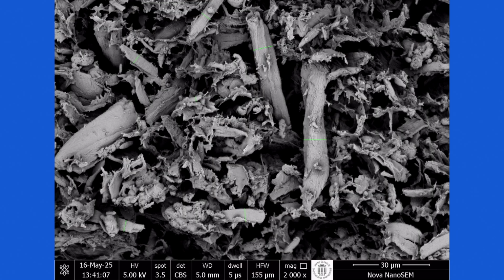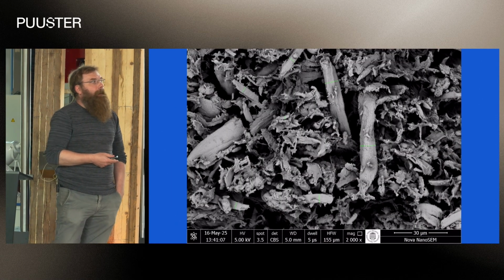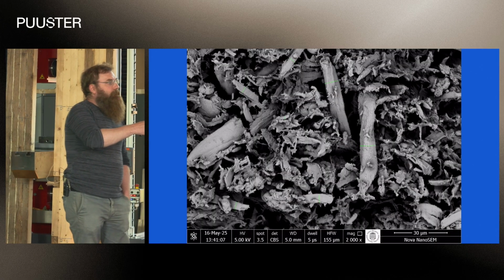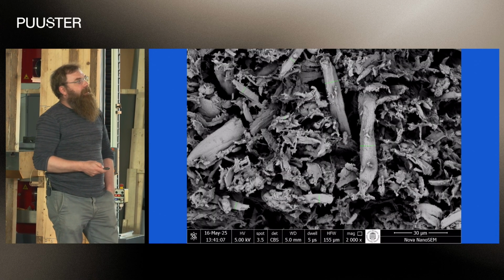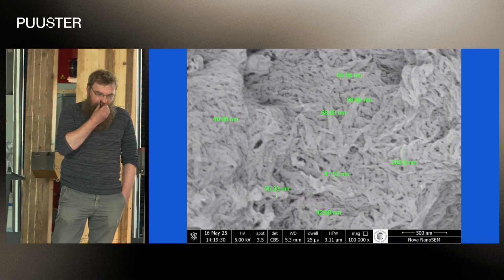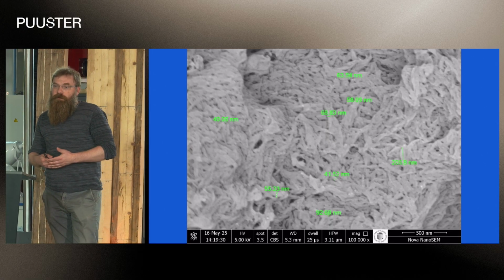So at the moment, here are some later results which we are doing together with the chemists who develop new processes of delignifying pulp materials, producing nanocellulose, and also developing new materials based on lignin and nanocellulose compositions, and using them as glues. And we can look at the material, let's say, morphology on a quite small scale. We are talking here around, like, here we have the scale bar, 500 nanometers, but we are looking at really small stuff. And very many times, the physical properties of the pulp materials start from the micro and nano scale. So to understand those.